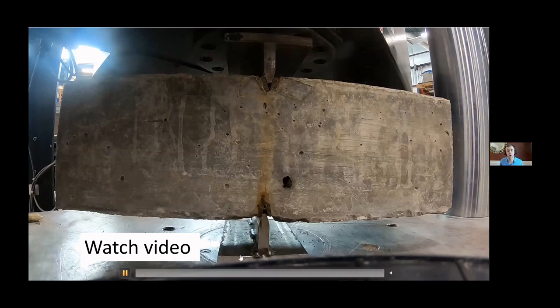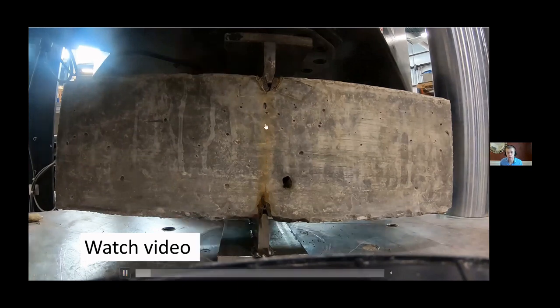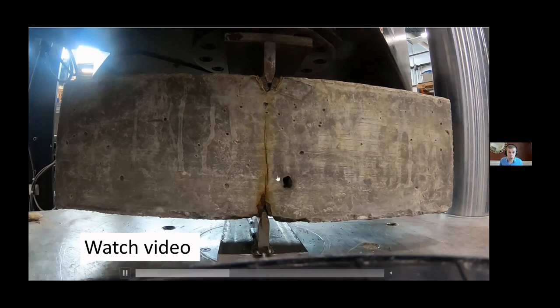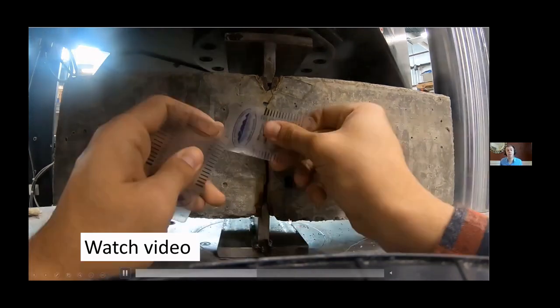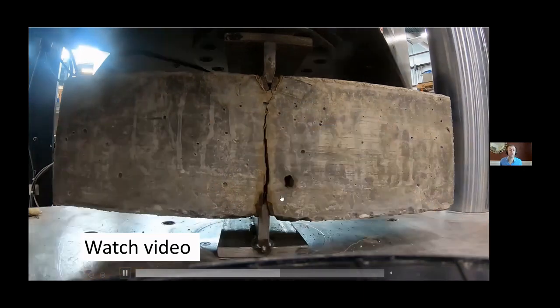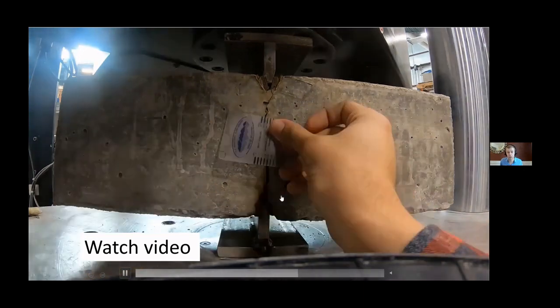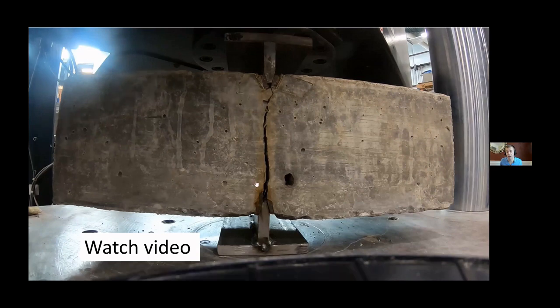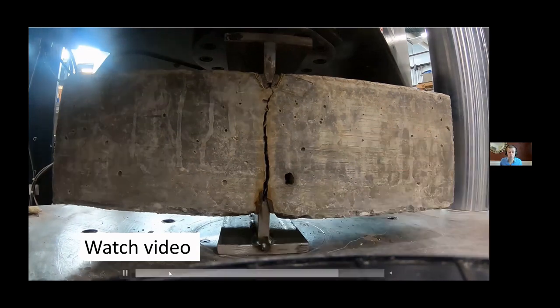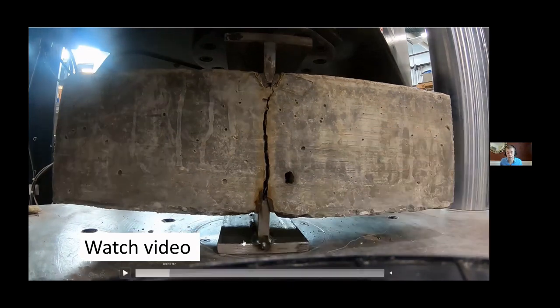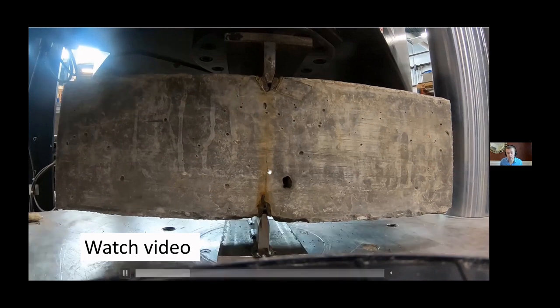So as it starts to go in here, it's loading, loading. You see the crack creep, creep, creep. And we're actually measuring it. We're using a crack card to measure it in 3 different places on the top and on this face, and 3 different places on the back face as well. And so we can see for a given amount of load how much cracking. We'll watch that again. Here it is. We're measuring the sizes of the cracks.